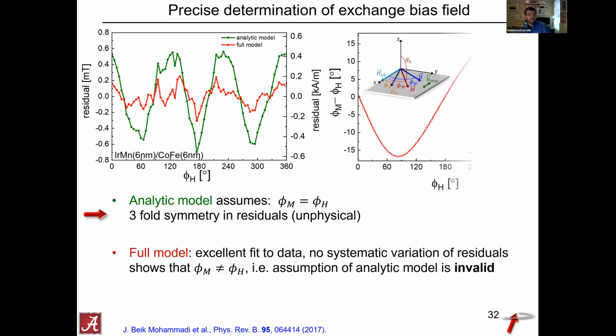The full model then helps us explain where that comes from. It comes from this assumption that the magnetization is aligned with the field, which is only fulfilled at 0 and 180 degrees. In between, the magnetization at any finite field will always deviate from the field direction. So that's something one should keep in mind when using this analytical model. It's pretty good to get a good estimate at first, but then you can do better by using the full model.